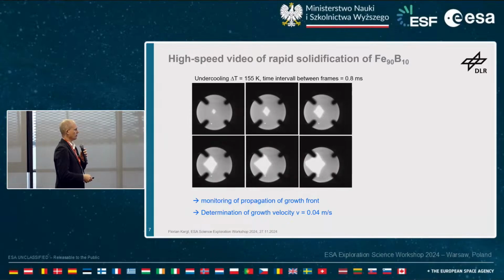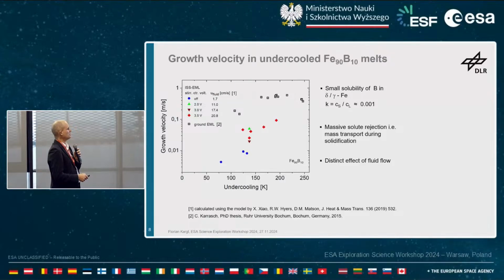And from that you can derive the growth velocity that is, I would say, not very fast. I mean, you can have meters per second growth velocities in some systems, and then you have systems that are a little bit slower, like the iron boron system. So the point here is, for these relatively moderate velocities in this space station experiment with low fluid flow, that you have in the system a small solubility of boron in the iron, which means during the growth of the iron, you have to enrich the solute ahead of the growing crystal, and you have to transport it away in order to get fresh iron towards the interface for the crystal to grow further. If you have no fluid flow in an EML experiment, like you have on the space station, then it's more or less diffusive.